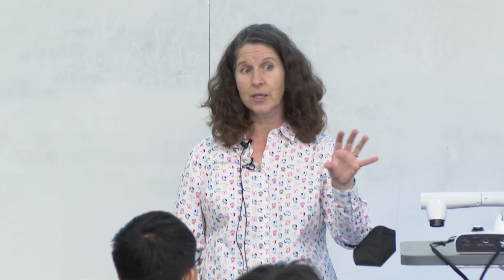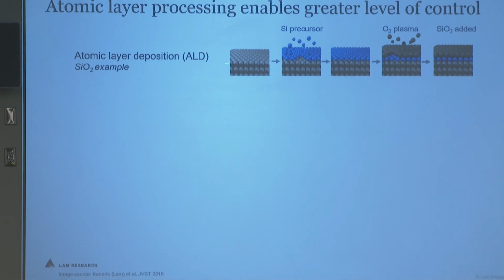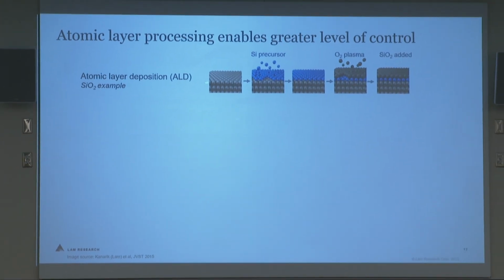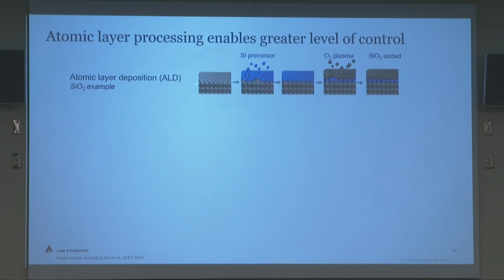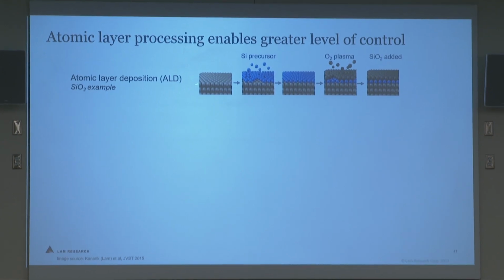So the difference between a continuous process and the atomic layer is these steps are individually separated from each other. So for the deposition example, you bring in a silicon precursor. It's usually an organometallic. It's a silicon that's bonded to, let's say, an amino group or some other labile group with carbon, nitrogen, hydrogen. And in this example, you bring in an oxygen plasma that reacts and strips off that excess, but leaves only the silicon, and the oxygen bonds with that silicon to create your silicon dioxide.